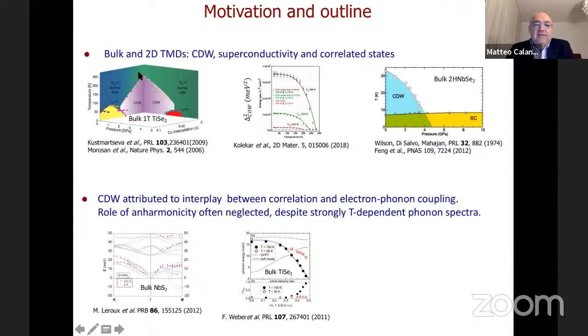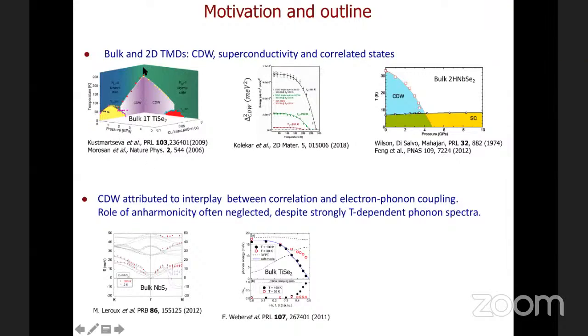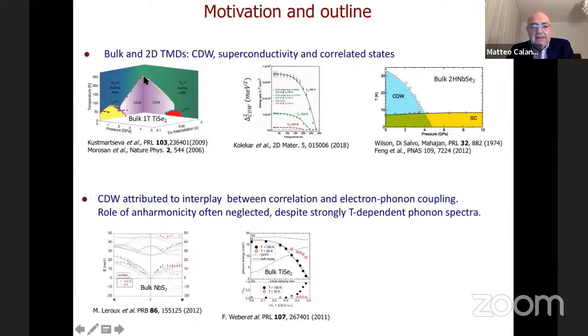For example, this is the phase diagram of bulk 1T titanium diselenide. On the z-axis you have temperature, here you have copper intercalation, while here you have pressure. I guess you see my mouse, no? Yes. And at x equal to 0, there is a charge density wave with critical temperature approximately 200 K with a 2 by 2 by 2 structural distortion.